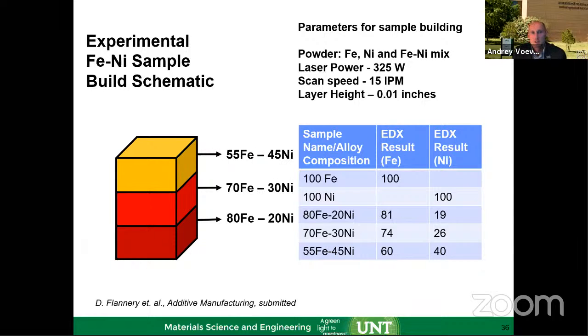So that's the selection. And when we're running, for example, Ti6-4, we see titanium, we see vanadium, we see aluminum. Now we have 3 peaks to track. But we also wanted to change from one powder composition to another, so we found iron and nickel to be one of the suitable systems to do that.